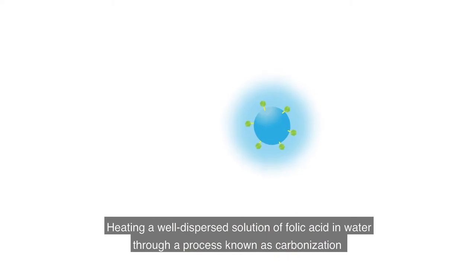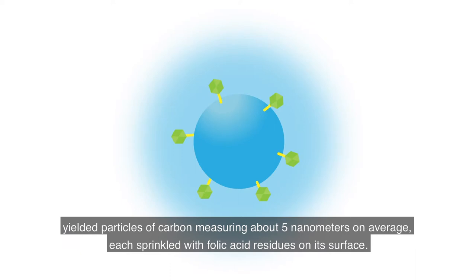Heating a well-dispersed solution of folic acid in water through a process known as carbonization yielded particles of carbon measuring about 5 nanometers on average.